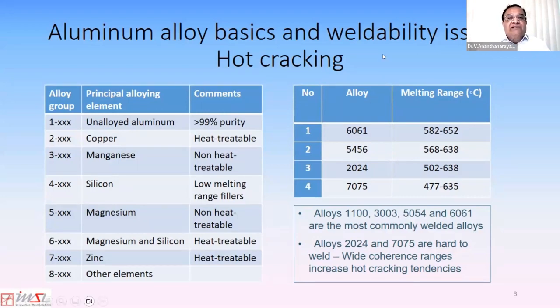So what differentiates these alloys are, firstly, whether they are heat treatable to high strengths or not. And you can see here that 2000, 6000, and 7000 series alloys are the ones that are heat treatable. And the 2000 and 7000 series alloys are not considered very weldable. So they're used mainly by the aerospace industry. We all have seen aircraft body panels being riveted and not welded because of the weldability issues with these 2000 and 7000 series